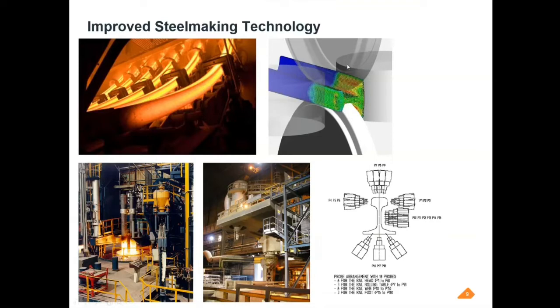At the top right, you can see universal rolling of rail was introduced. So universal rolling is rolling it in two planes simultaneously. So you have vertical spindle rolls there and horizontal spindle rolls there. And what this allows you to do is control the dimensions incredibly accurately. And that's most important for higher speed railways. For example, the TGV network in France, 320 kilometer an hour cruising speed, you need to have a very dimensionally accurate rail, because rail to rail, when you join them, you need to have consistent dimensions so you don't end up with a little step or misalignment of your welds.